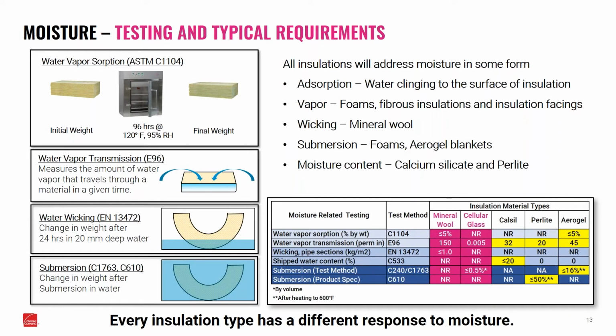Submersion methods: if you go down to ASTM C240, which relates to foam and cellular glass, that's going to be 0.5%. Because it's a glass product, it's just not going to absorb any water. Really, the only water it picks up is whatever surface contact or surface tension it has that stays on that surface. So those numbers are really low. You look at something like aerogel, and it can be as high as 16% moisture content. And again, that's after it's been heated to 600 degrees Fahrenheit, because remember, we don't have any waterproof insulations with the exception of cellular glass above 600 degrees. Now, prior to putting that in, conditioning it, that requirement would be more like 8%.